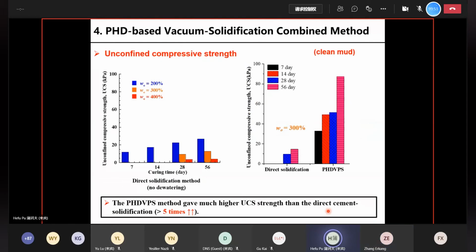We'll also look at the unconfined compressive strength. On the left, you can see the direct solidification method without prior dewatering. We tested different initial water content, and you can see that the solidified strengths decreased significantly with increasing water content from 200% to 400%. So this tells us how important it is to lower the water content for further treatment.